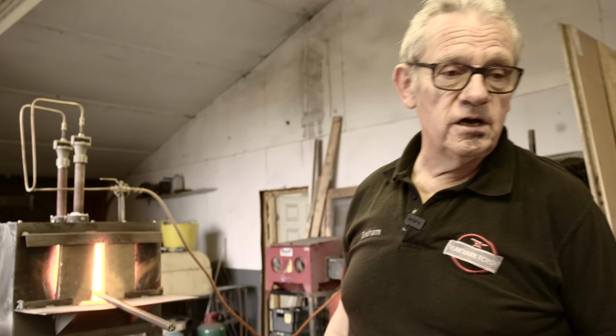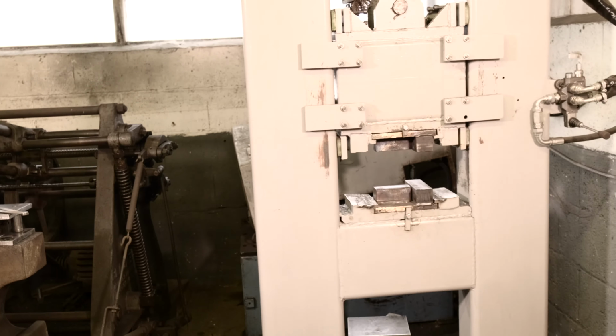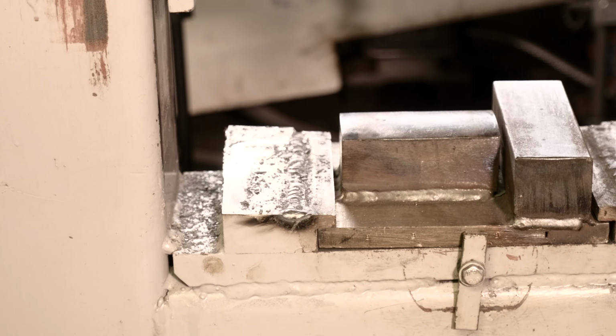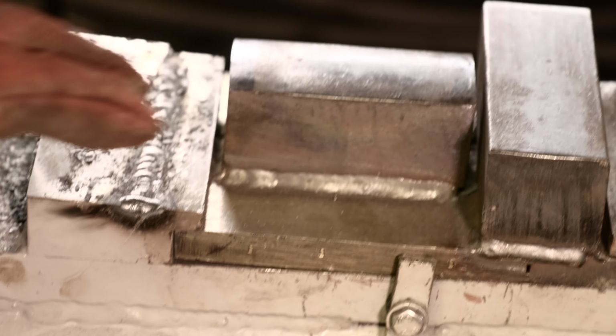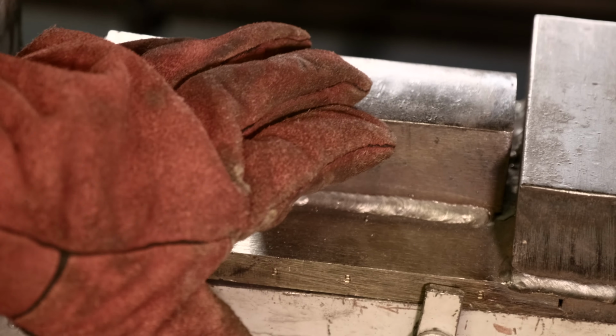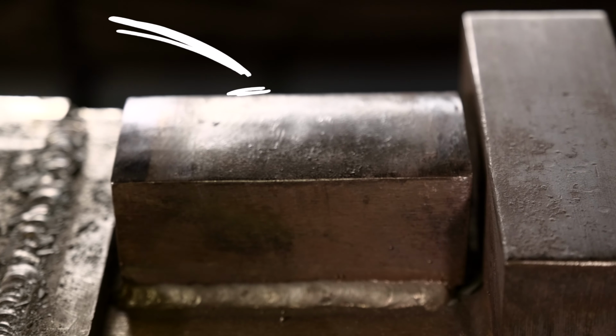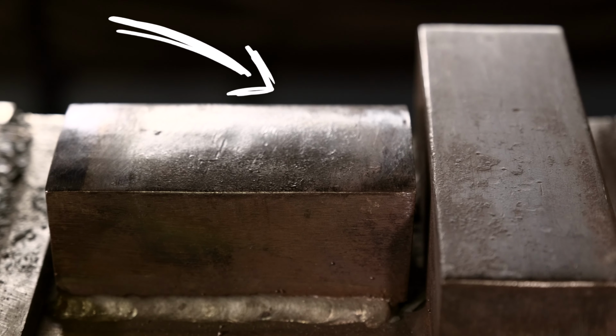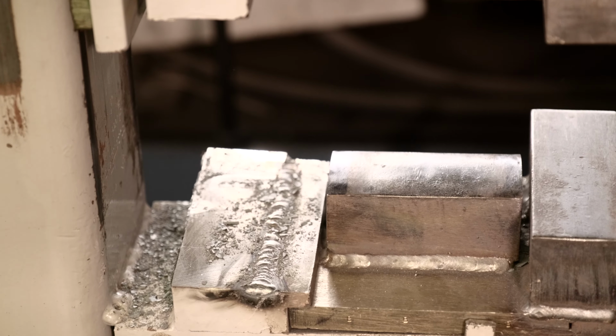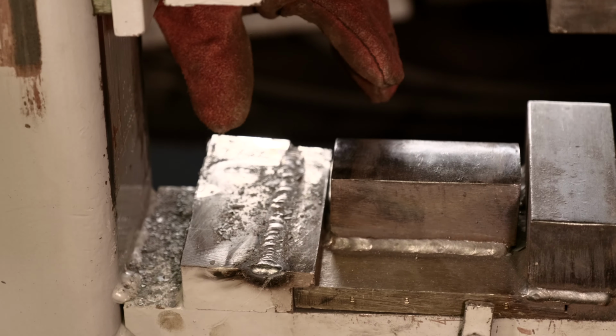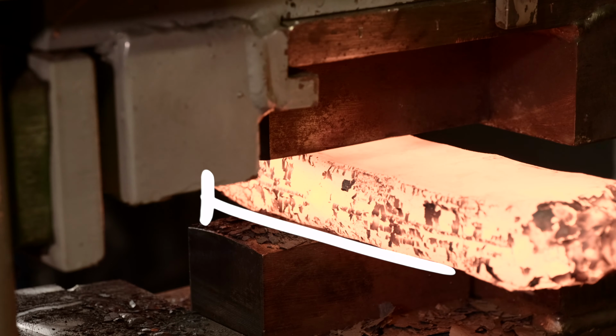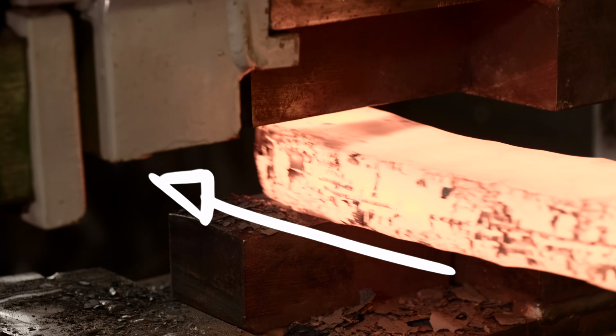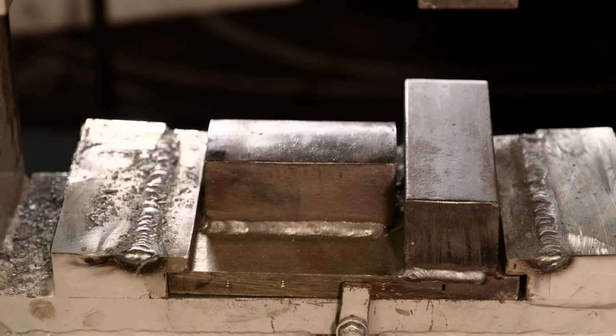Now if you have a look at the press behind you, you'll see we've got 2 pairs of dies in the same set. The one on the right hand side is completely flat. We just use that for flattening, straightening and keeping the billet in good order. The ones on the left hand side are radiused. If you look at the end you can see it's slightly radiused on the top, and the upper die is exactly the same. So when we press the metal in there, it stretches it out far more that way than it does sideways. And that's what we want. We use those dies for forging out the longer length.